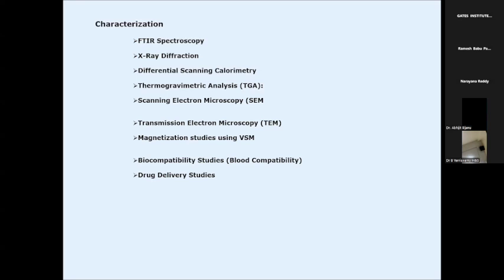Even the conversion of monomer to polymer, we have characterized using FTIR spectroscopy. Even the particle size, and whether the particles developed inside the hydrogels are crystalline or amorphous in nature, we can confirm with X-ray diffraction. And thermogravimetric analysis we have done to see how much percentage of conversion you achieved in your polymer system, and how much percentage of nanoparticles was obtained in your hydrogel system. Then the glass transition temperature and crystalline temperature, everything we calculated using differential scanning calorimetry.